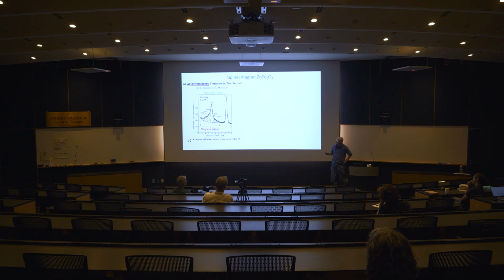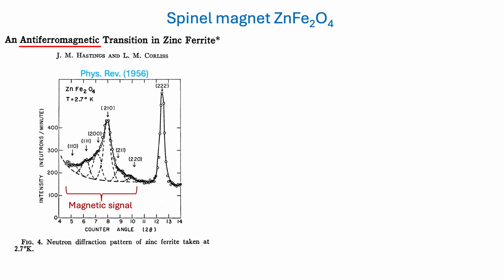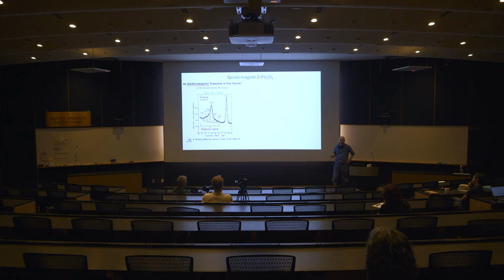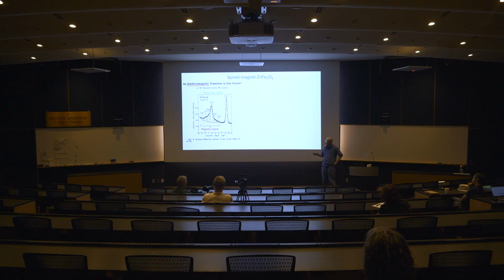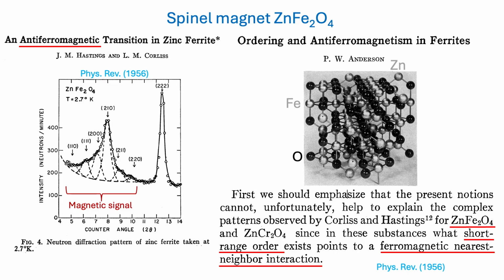So our choice at this moment is the spinel magnet ZnFe2O4. The Fe moment sits on the B site of the material, which is a pyrochlore lattice. And the antiferromagnetism was studied very quickly after neutron diffraction became a powerful tool in the field. So in 1956 there was already published data on that. However, you can see, compared with the lattice peaks, which are very sharp, the magnetic signal is very broad and diffusive. This actually is puzzling.